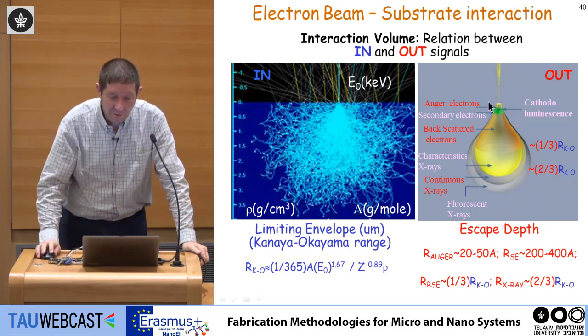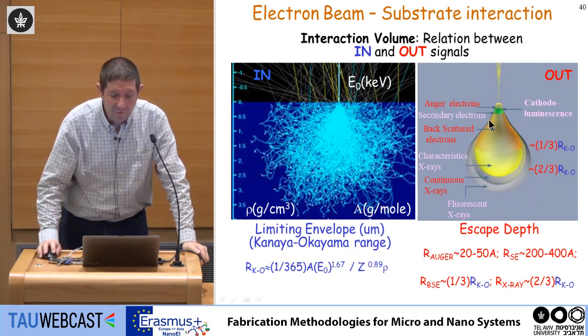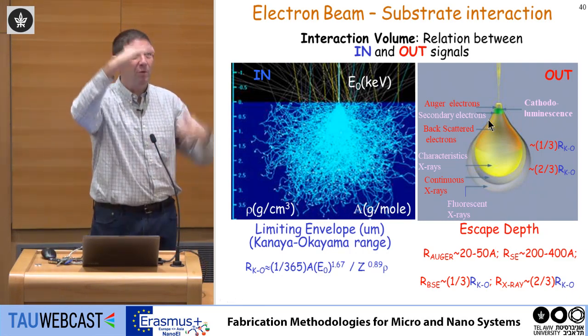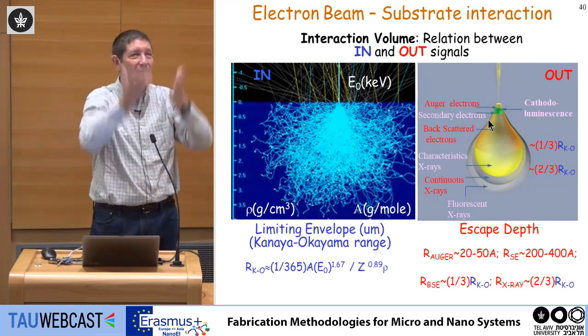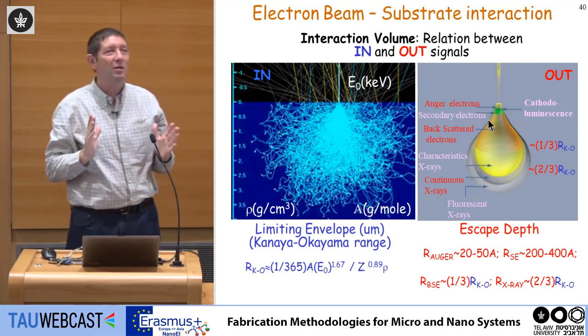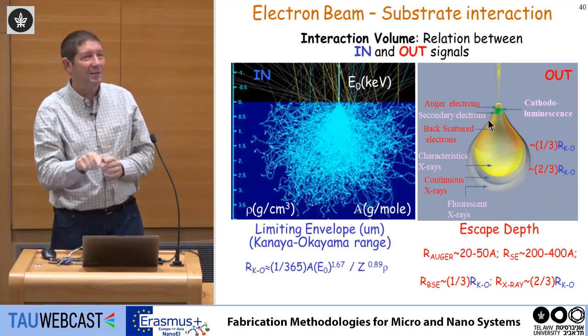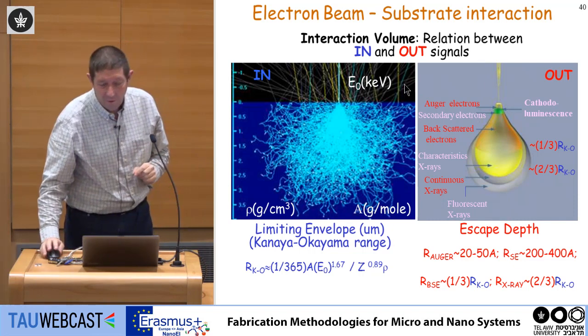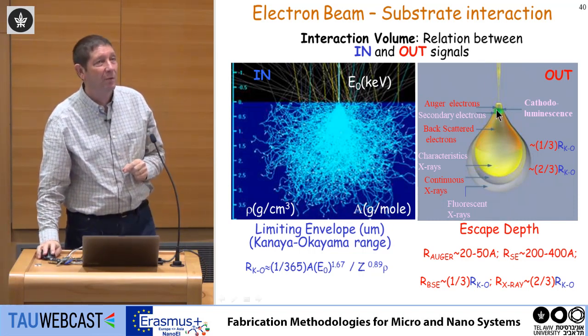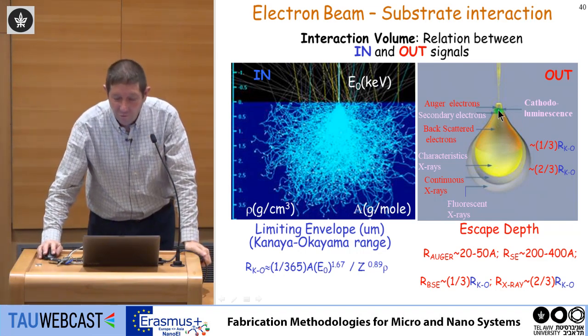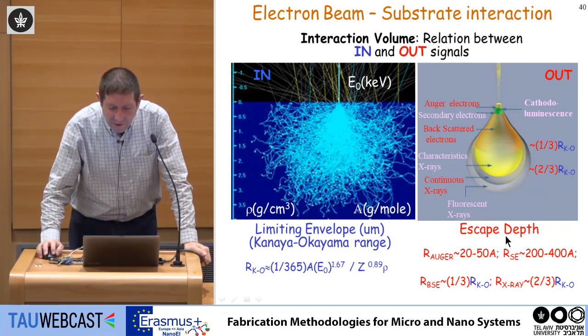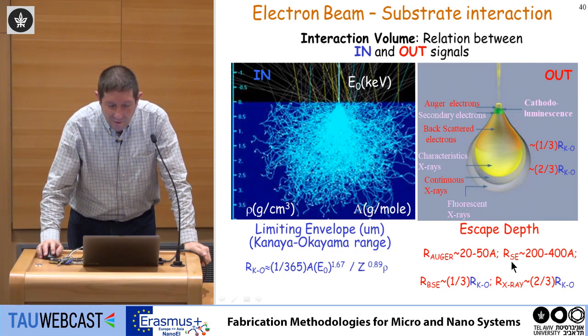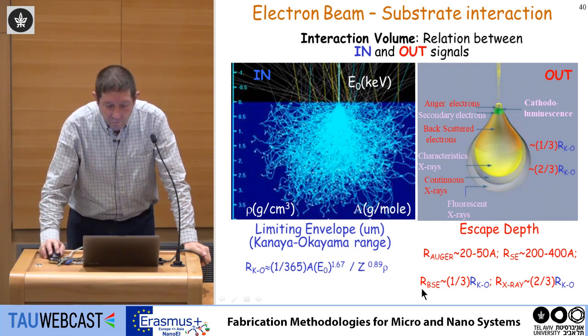But you have to remember, with this onion shape, you are collecting energy from a large volume. So if you have copper on silicon, you can actually measure electrons from various materials. The spatial resolution of the material analysis in this technique is not so high unless you are using the Auger electrons, which are very, very high resolution, only from the surface, but very few microscopes have it. So this is what we call escape depth. The Auger electrons escape from a volume of 2 to 5 nanometers, and the secondary electrons are emitted from a volume of 20 to 40 nanometers. And this is the backscattered electrons, and this is the X-ray volume.